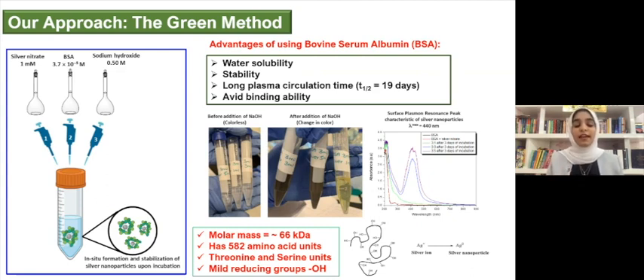So this was an indication after we added the sodium hydroxide and after we incubated it for 72 hours at 40 degrees Celsius. Then we observed a spectrometer graph using the UV-Vis spectrometer. We observed the surface plasmon resonance peak at 440 nanometers. And this was the second indication that we successfully synthesized silver nanoparticles. So what we assume happens here is when we add the sodium hydroxide, the protein unfolds. And when it unfolds, it exposes these hydroxyl groups, which then reduce our silver ion into a silver nanoparticle.